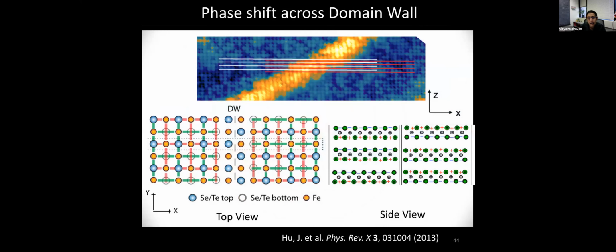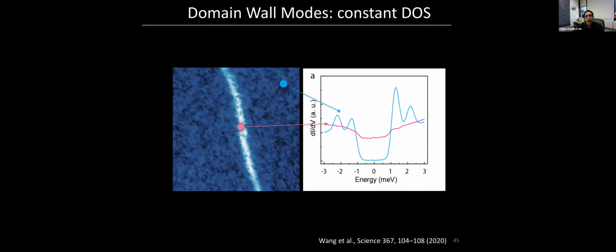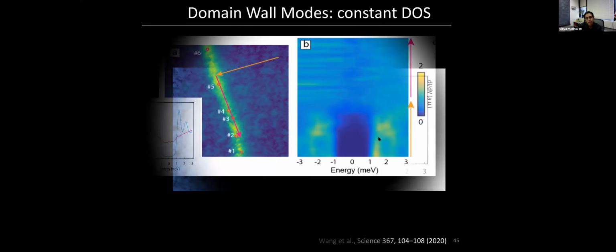So now we can ask, what do we see when we go to such a domain wall? And so here's what we see. Far away from the domain wall, we see a nice superconducting gap with actually 0 density of states. And if you go to the domain wall, you see the gap, but then you see this flat density of states inside the superconducting gap. So the superconducting gap is filled up. You have a finite density of states, but it's a flat density of states.